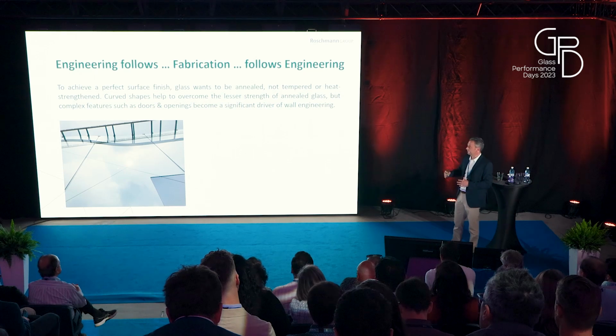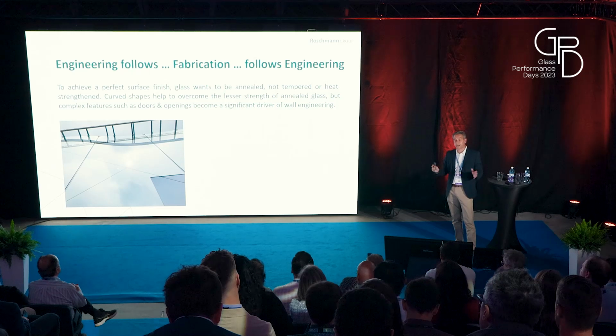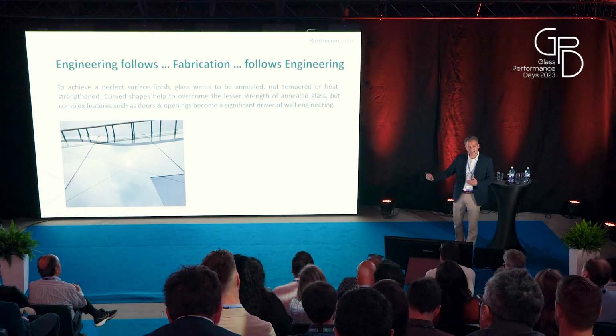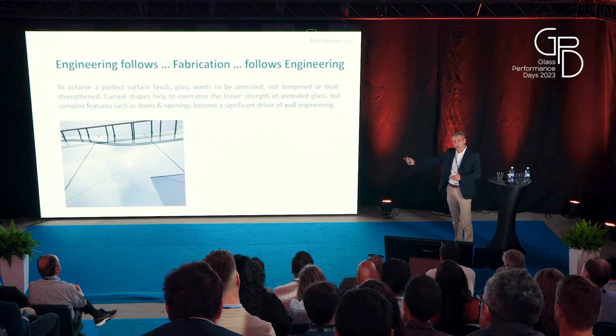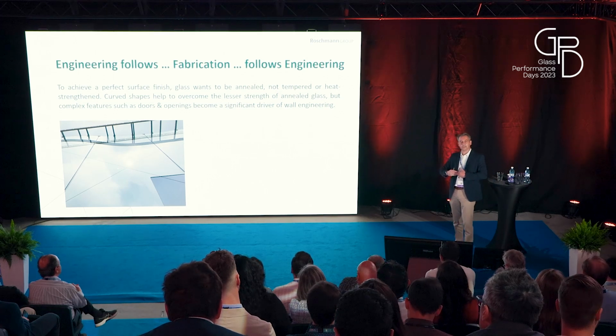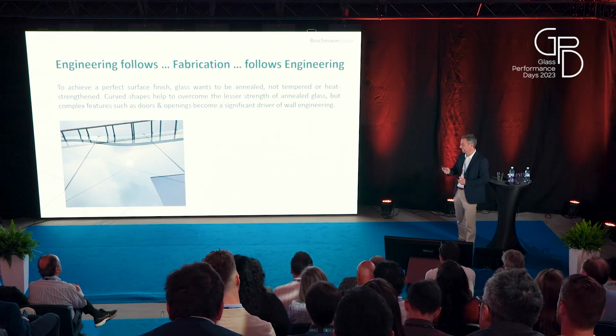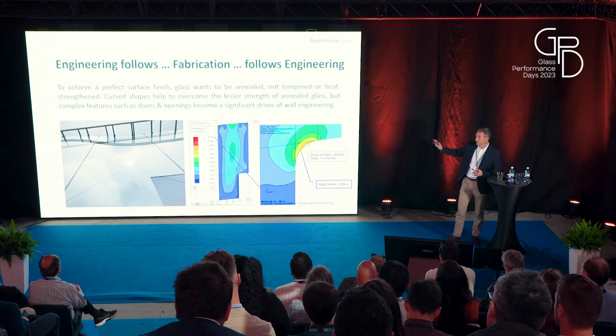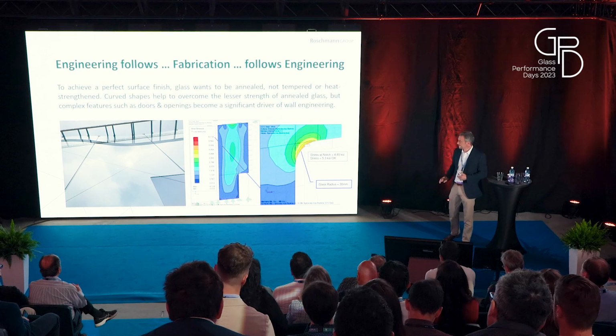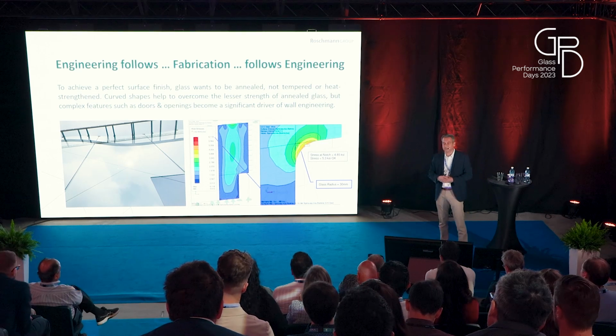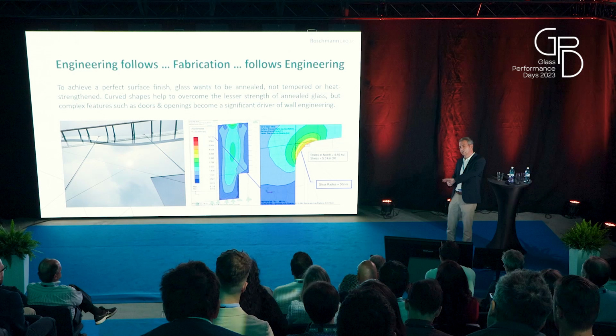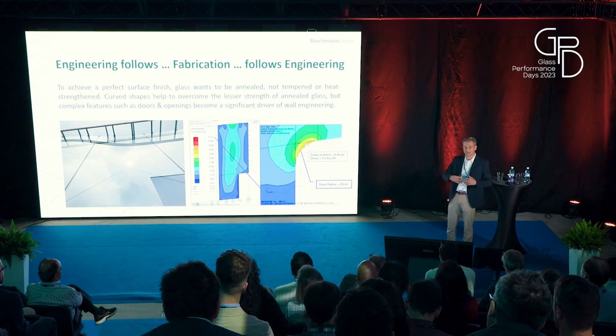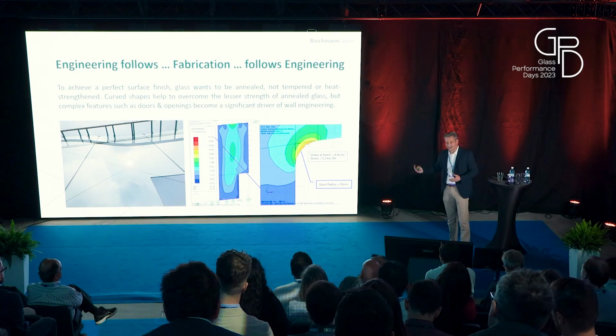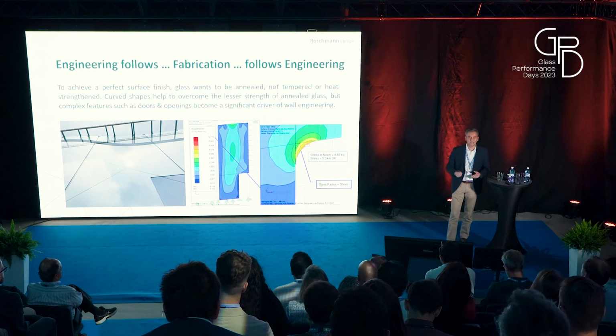I really want to have a clean, crisp facade where I am putting a notch into the glass. So, okay, if I'm putting a notch into the glass, then I'm hitting a roadblock in engineering, which again goes back to the technology I am given to actually fabricate the glass. There is a possibility of doing notches in glass that can be engineered, but from a technology point of view, it already crosses out several fabrication technologies like the warm bend slump glazing.